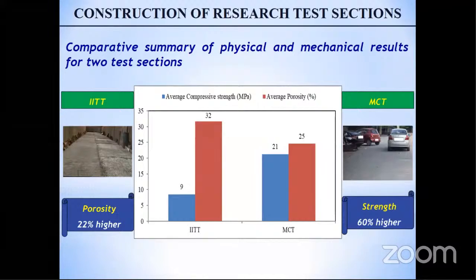This is a small comparative summary between the physical and mechanical characteristics for the 2 test sections, one at IITT and the other one at Municipal Corporation of Tirupati. So this blue bar actually presents the compressive strength, and the red bars present the average porosity. As can be clearly seen, for the test section that was constructed in Municipal Corporation of Tirupati, the compressive strength was of the order of 21 MPa. Whereas the one at Indian Institute of Technology, Tirupati, the compressive strength was on the lower side, only about 9 MPa.